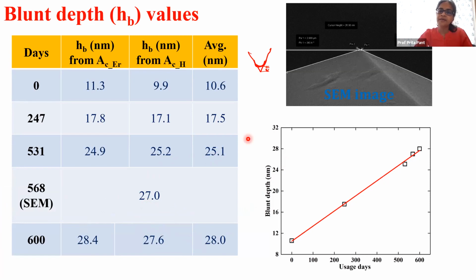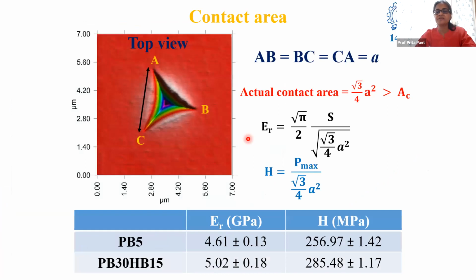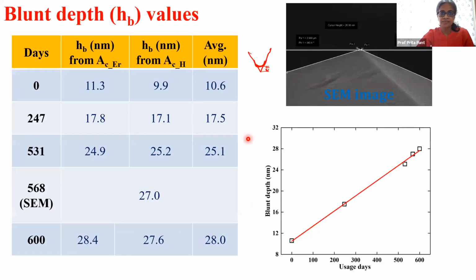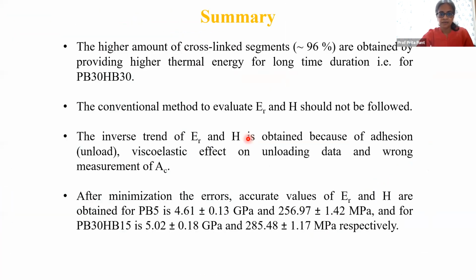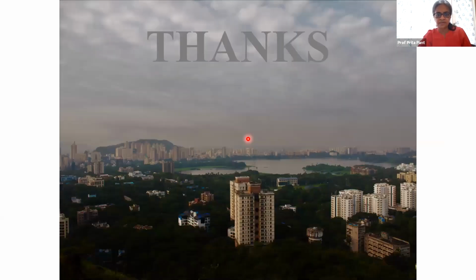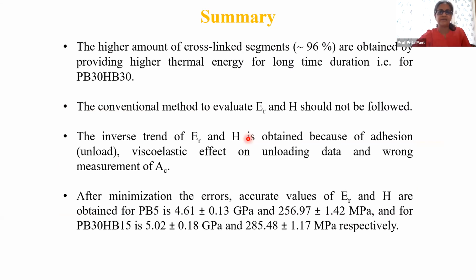And so either you're able to correct for this in a manner which is better than the current recipe, or you just go ahead and measure this area of contact and do a calculation of your hardness and modulus. This works for us. Sorry, I thought I had a slide on recovery, but I think I've pretty much reached the end of my speaking time, so I'm going to stop here. I don't have the recovery slide, so I'll leave that.